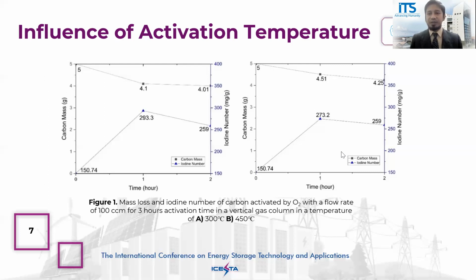The TPD analysis showed that the black carbon began to decompose at an onset temperature of 600 degrees C, and 630 degrees C for the TGA analysis. The degree of mass loss of carbon activated at 450 degrees C was slower compared to that activated at 300 degrees C. That also impacted the corresponding iodine number. Basically, the iodine number decreased after reaching the maximum value due to the absolute volume of macropores with the increase of burn-off. From this result, it is concluded that the best activation temperature in this work is 300 degrees C.